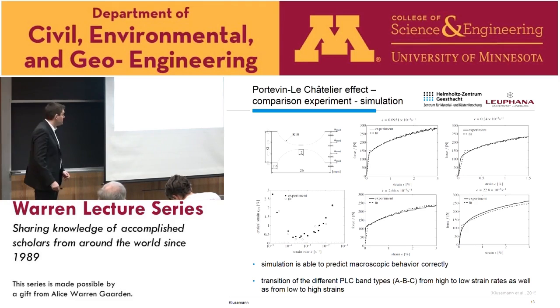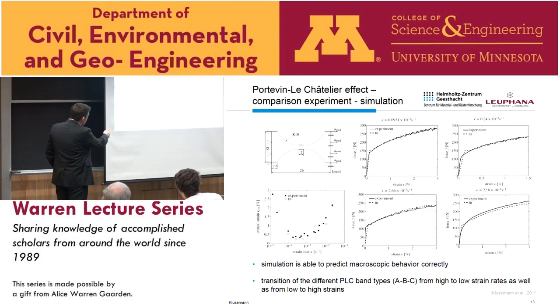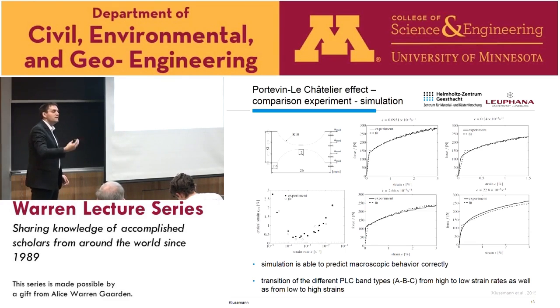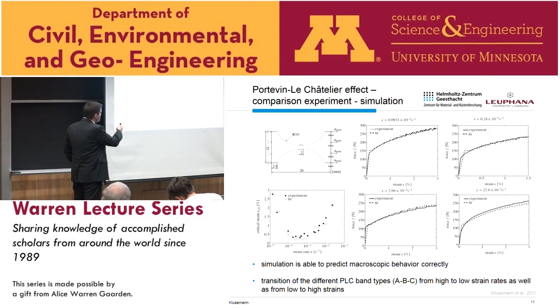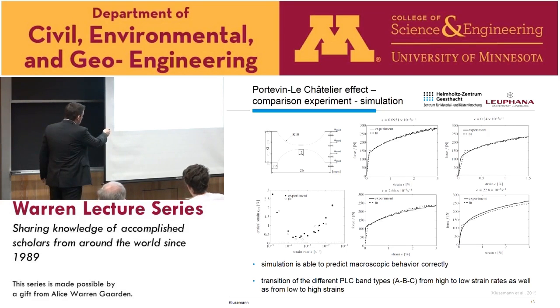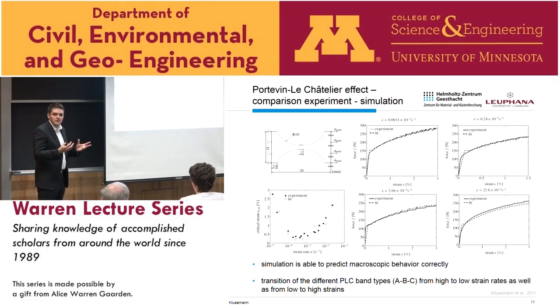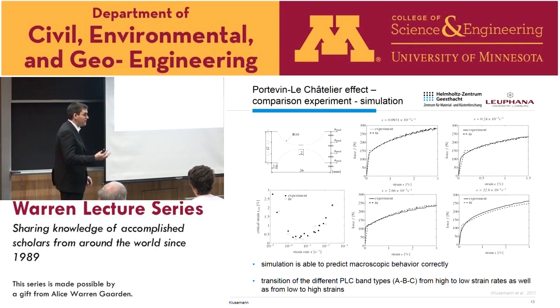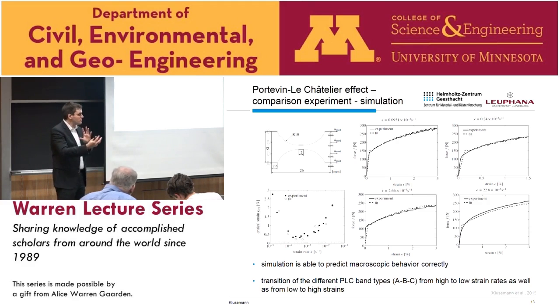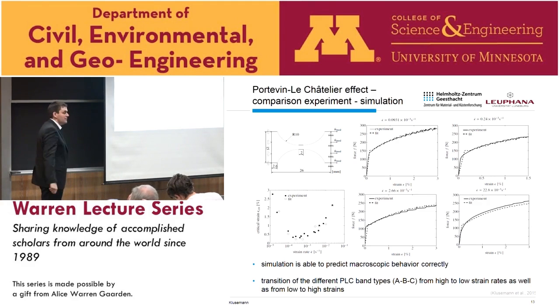One important thing which I just mentioned is this plot where you have the critical strain over the strain rate. First of all, you see of course that we have this decreasing critical strain with decreasing strain rate, but then also the inverse behavior, so we have an increase again of the critical strain with further decreasing the strain rate, which is not classically done by these kind of models. So usually they show this behavior which is just always decreasing. So first of all, we could show that by identifying the material parameters correctly, we are able to predict the macroscopic behavior correctly, and we are also able to predict this transition between the different modes, different PLC bands, from high to low strain rates correctly. And I will show you in a minute that it's actually also true for low to high strains, because there we have also an additional change.